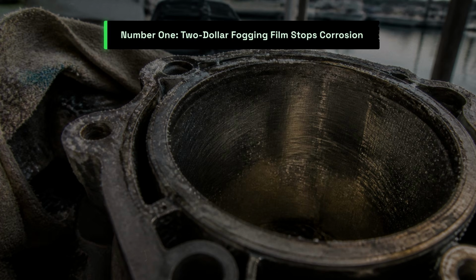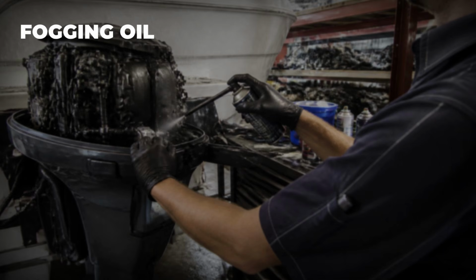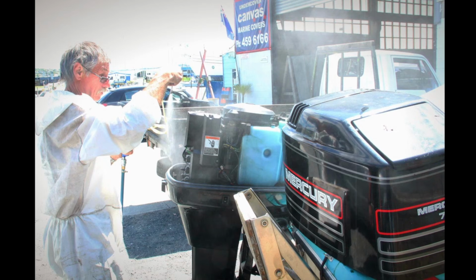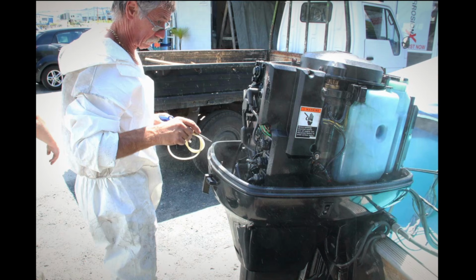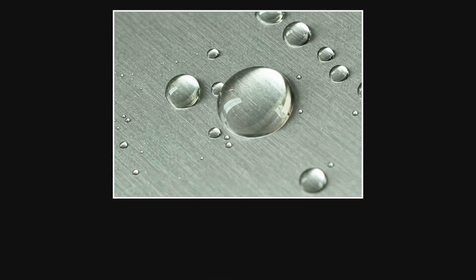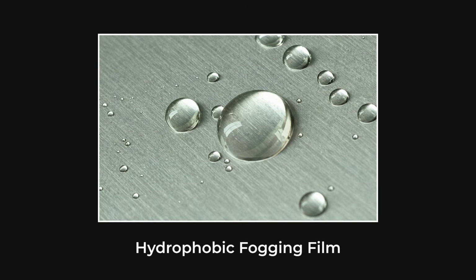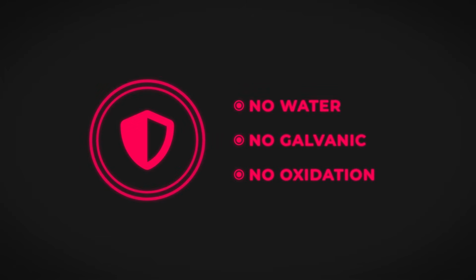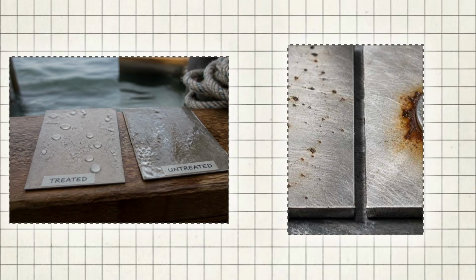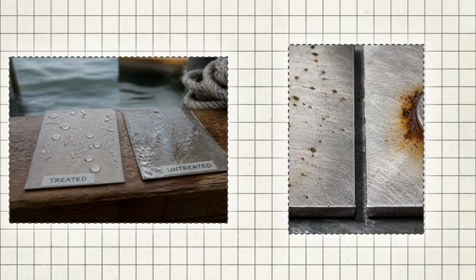That's the corrosion nursery. Corrosion-inhibiting spray, marine fogging oil for the internals, and a light anti-corrosion film for the external power head and electrical connections does one simple thing. It lays down a hydrophobic barrier film that physically separates the metal from moisture and oxygen. No water contact, no galvanic cell, no oxidation. The salt can sit there all winter and it has nothing to attack.